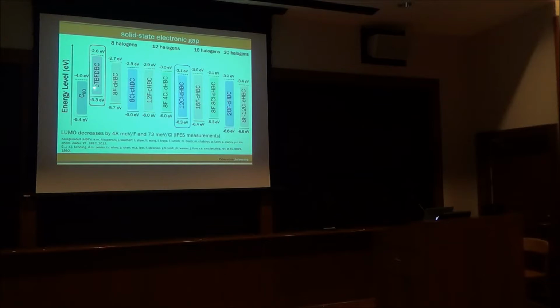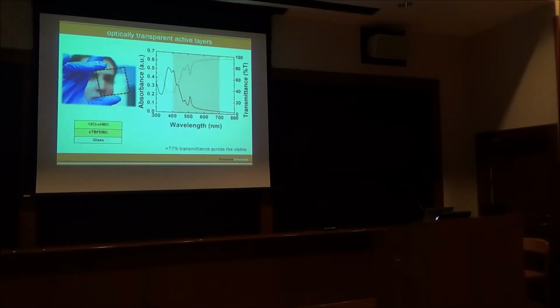We wanted to optimize, and we chose initially to show you the donor, and this 12Cl is the acceptor. This is Nick Davey holding one of these films, a stack of donor and acceptor. If you look at the absorbance and the transmittance, you can see that we're above 75% transmittance across the visible. So we're achieving what we'd like to do.